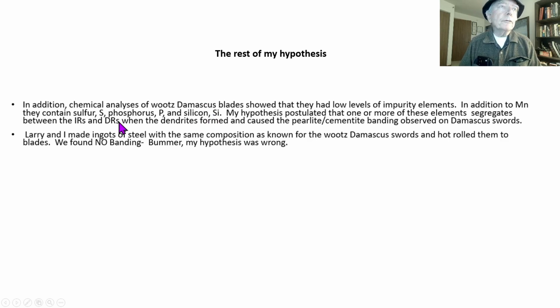Now, here's the rest of my hypothesis. In addition to what we said earlier, chemical analysis of Wootz Damascus blades showed that they have low levels of impurity elements in them, just like the low carbon steels. In addition to manganese, they contain elements like sulfur, phosphorus, and silicon. So my hypothesis is simply this. One or more of these elements must segregate between the interdendritic and dendritic regions when the dendrites form, causing the pearlite cementite banding that is observed on Damascus swords.